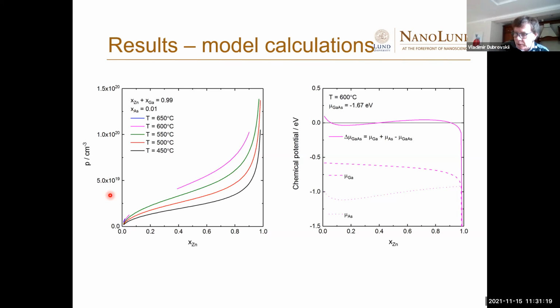Yeah, we have observed that. About 10 years ago, here, beryllium doping of indium phosphide nanowires by MBE changed the growth regime. It became nucleation limited at high doping levels. So the nanowires were grown much shorter compared to undoped nanowires. Yes, I have seen that. For beryllium, yes. For zinc, I don't know.